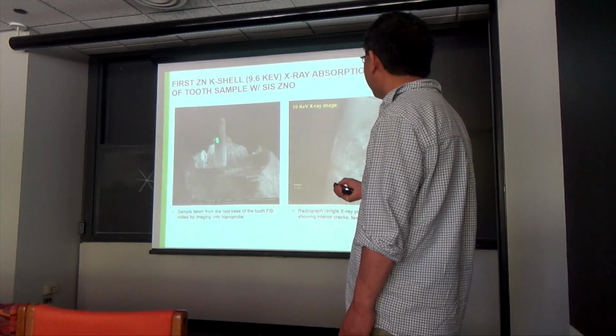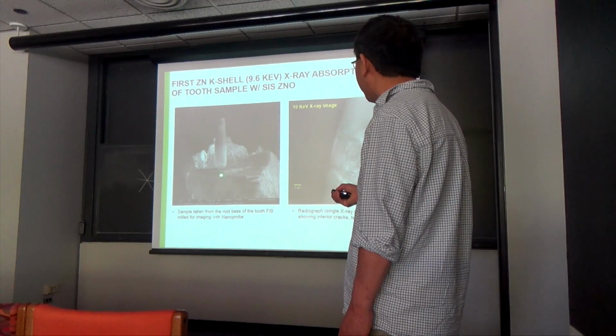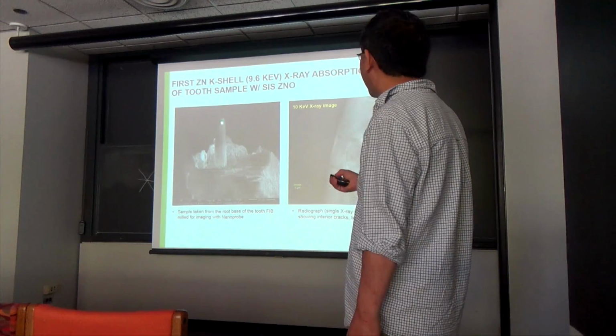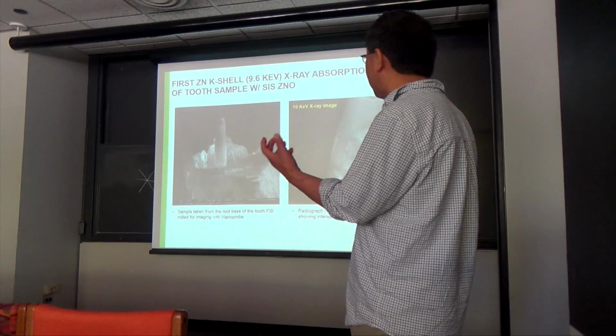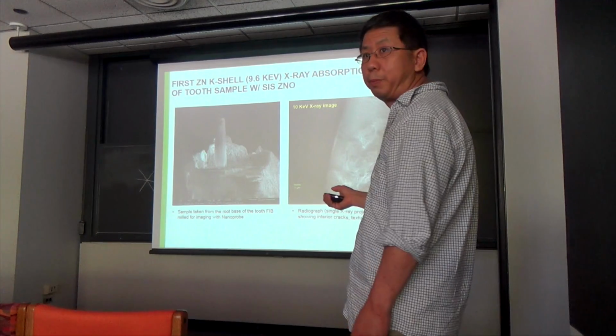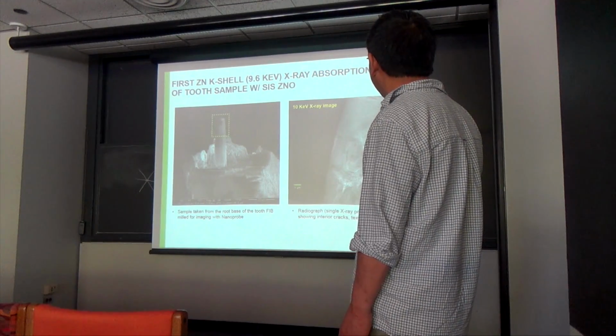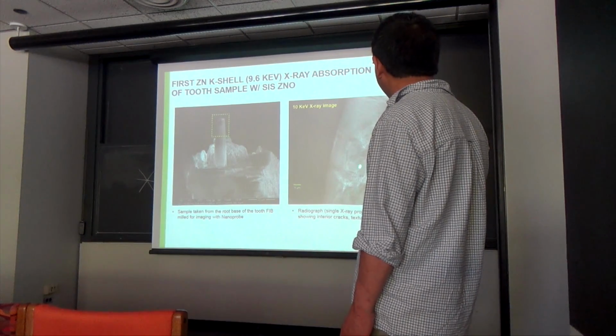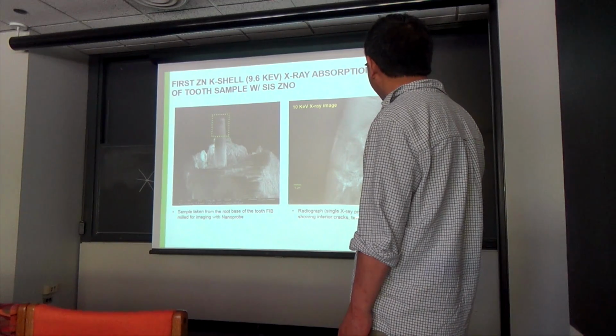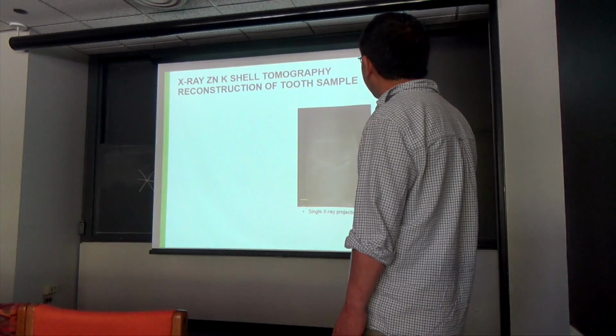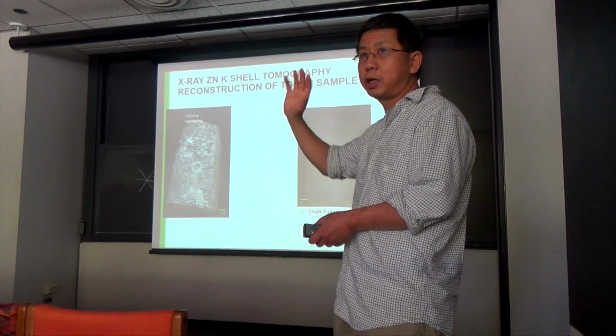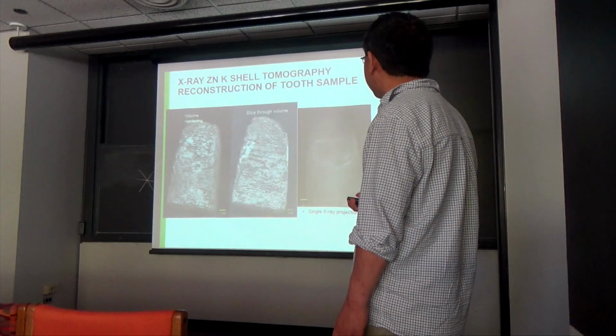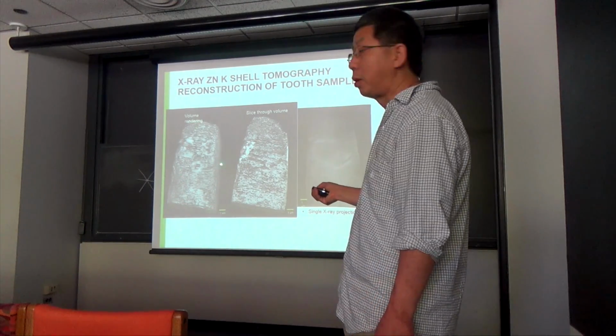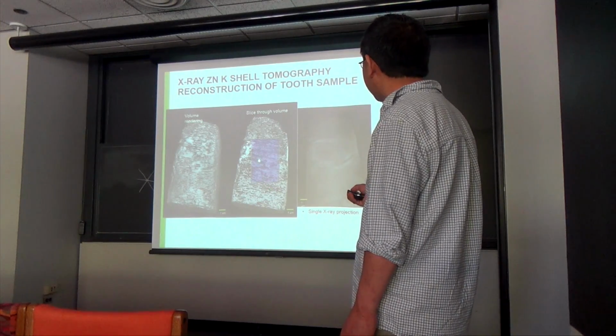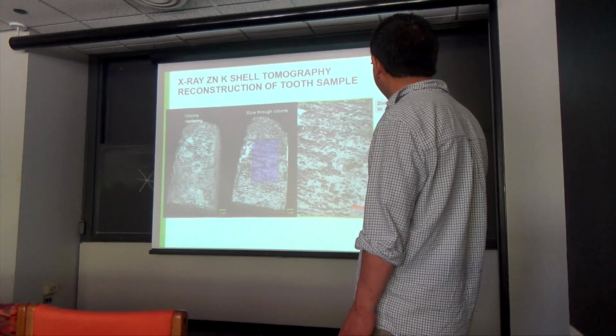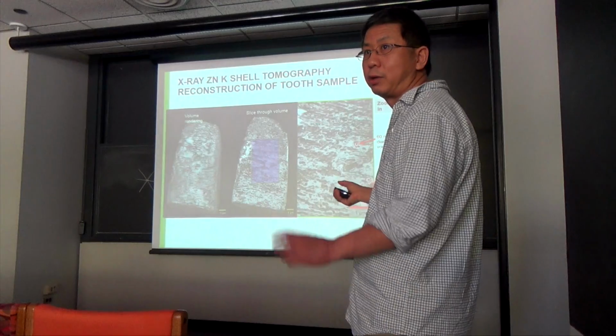So this is a little tooth that they used a focused ion beam to mill to a certain thickness, so this becomes a slight pillar. Then they take this tooth sample to the nanoprobe beamline. This is the first sample. The first image is a single shot of the image. You can already see internal cracks and textures in these teeth. But if you turn the sample, collect multiple angles, and then reconstruct, you can see even better. This is an X-ray tomography image of this tooth sample, a single slice of a very small area. You can see very tiny structures down to 60 nanometers. Pores and everything you can see very clearly, right?